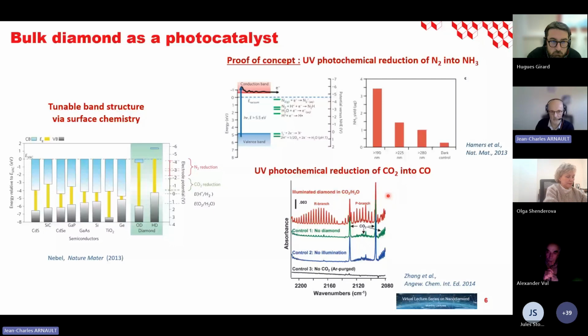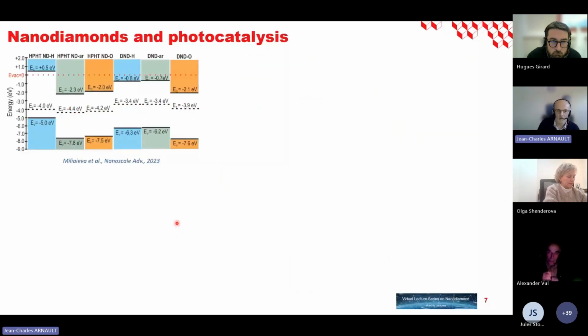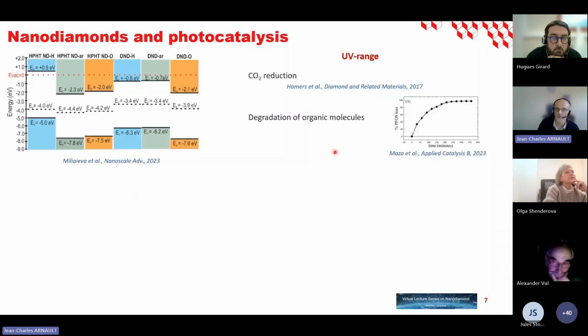What about nanodiamonds? It's quite recent, 2 or 3 years ago, and this is work from the Prague group, they evidenced by a UPS XPS study that for nanodiamond, we have similar behavior, so this sensitivity to the surface chemistry to shift the band structure. Based on that, there were some proofs of concept using the UV range. The first one was also from Hamers' group, using hydrogenated milled nanodiamonds for CO2 reduction. And more recently, an American group, Mazza and co-workers, showed that it's possible to use hydrogenated detonation nanodiamond to degrade organic molecules.